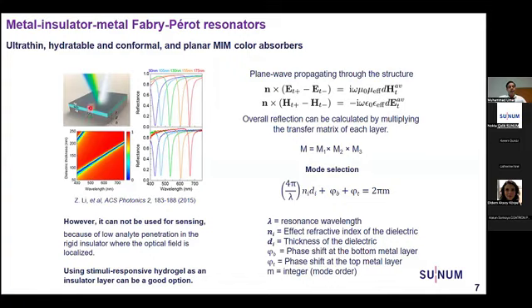So if the bottom layer is 30 nanometers or thin, it is called a color filter; it transmits the light. If the thickness of the insulator layer is increasing, the resonance peak of the device is also shifting. So this means that by tuning the thickness of the insulator layer, we can tune the resonance shift of the device.